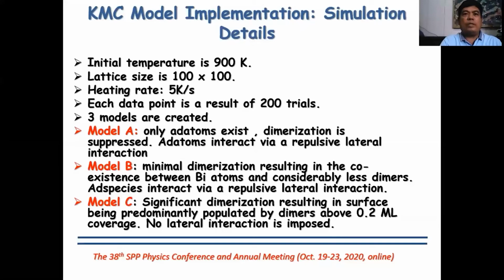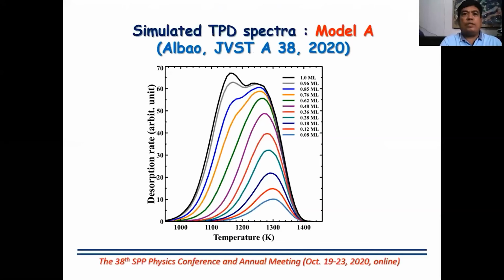Model B: minimal dimerization, resulting in the coexistence between bismuth atoms and considerably fewer dimers, Adspecies interact via a repulsive lateral interaction. Model C: significant dimerization, resulting in the surface being predominantly populated by dimers above 0.2 monolayer coverage. No lateral interaction is imposed. And here are the results of the simulation.